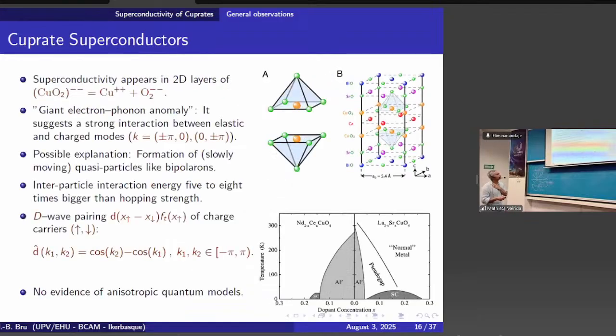One thing that I should also mention: I speak about an integer number of particles in each lattice site, and in the first part of my talk I was speaking about 2D. So what is 2D here? This is the structure of one cuprate. What all cuprates have in common is that they always have a layer of copper and oxygen. This layer that you see in orange and green is copper and oxygen, and they all have this two-dimensional layer. This is my 2D, because in the superconductor the transport is shown experimentally to take place in this two-dimensional layer made of copper and oxygen.